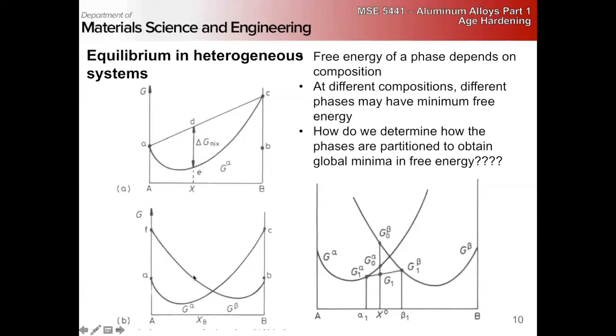In this case, we have an alpha phase that's a potential and a beta phase that's a potential. Well, at low concentrations of B, we can clearly see that the alpha phase has a much lower free energy. And at low volume fractions of A, we see that the beta phase has a minimum free energy. But what about when we're somewhere in the middle? If I'm at a point, say here, how do I determine how it's going to be partitioned into alpha and beta phases? This is where our common tangent construction comes in.